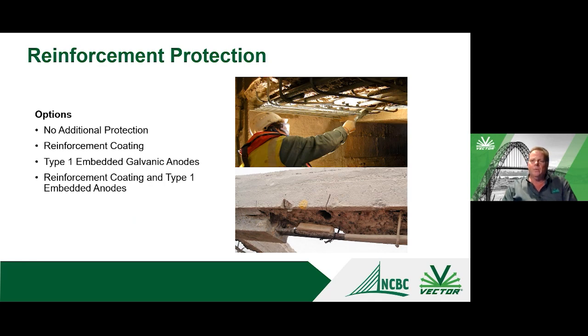But there's times when you may want to look at different philosophies on reinforcing protection. You may still want to provide additional protection to the exposed reinforcing in the area. You can use epoxy coatings, field applied, just to provide additional protection. You may want to look at that if you have areas of low cover, just to give you some additional protection. And we'll talk a little bit about embedded galvanic anodes.